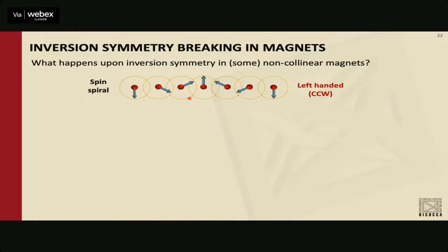So assume now you have a spiral. Spiral means that these are the lattice sites, like iron and manganese, and then your spin moment is rotating from side to side. So you will get a spiral. This is, I don't know, clockwise, counterclockwise. Right? It's rotating like this. Now, let's apply inversion symmetry. Inversion symmetry means that I need to move this atom from here to here, and from here to here. And so you will immediately see that it's not the same. So certainly the inversion symmetry is broken.